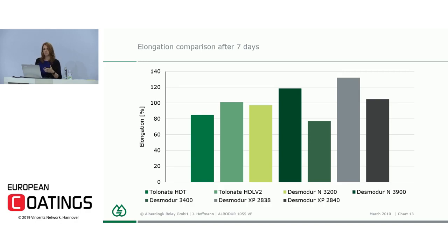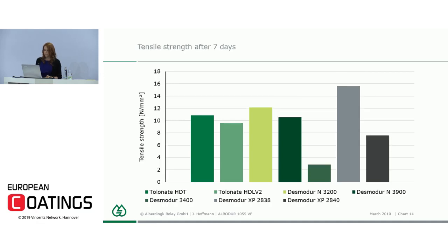So for example, the 2838, a lot of people think it's much harder, because the tensile strength is much higher, because you cannot bend the sample. But at the end, on a floor coating, you would not recognize that difference. You would recognize that on a roofing, where you really need a little bit more elongation and a little bit more tensile to overcome higher temperature changes. So here we see the big differences. We looked at the product very closely, and we think that because the 2838 is so extremely compatible and has IPDI, the tensile strength is very quickly activated and gives us that really fast performance.